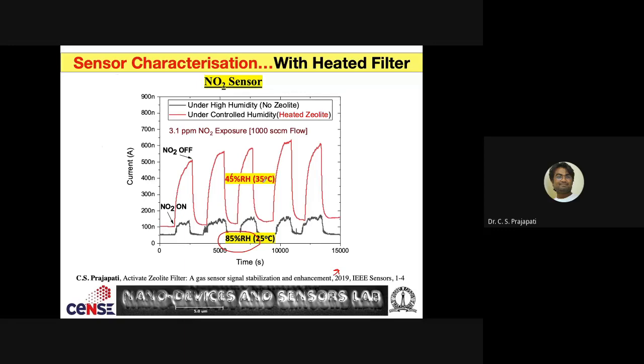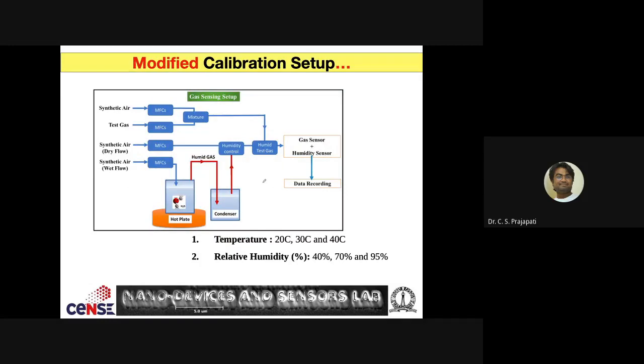Now, if you want to have different humidity, we need to have a setup, like a calibration setup. I just talked about the dry calibration setup a few slides back. Now it's a modified one where we have our own humidity control, which can control the humidity whatever way we want for the test system. So the earlier setup was this part, and now we added this part, and we can control the amount of moisture we want during the calibration.